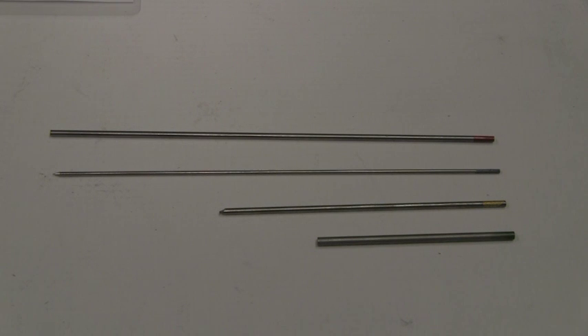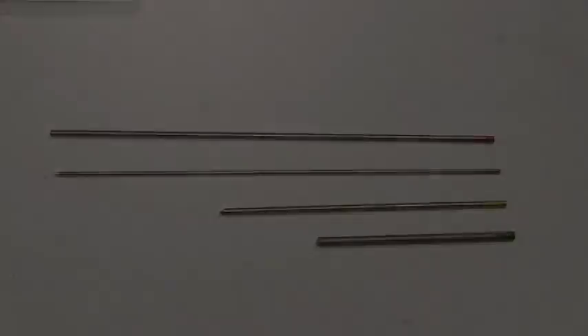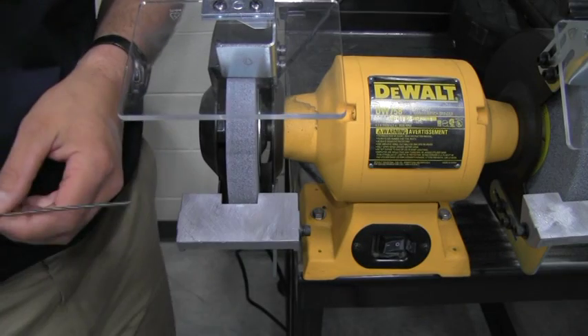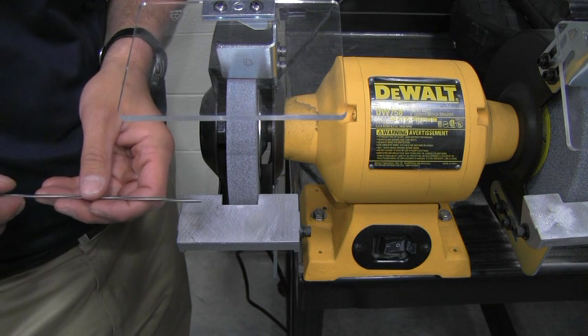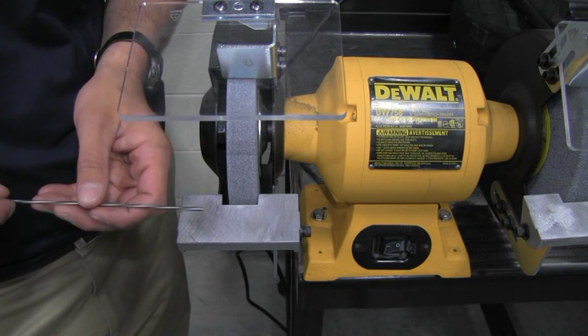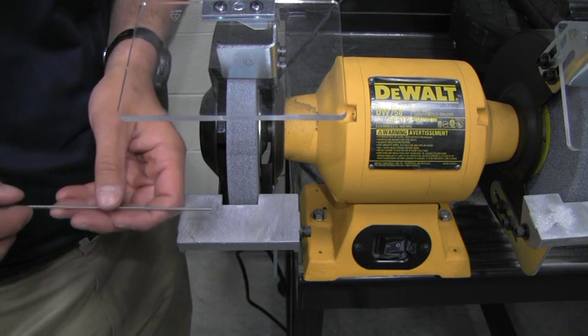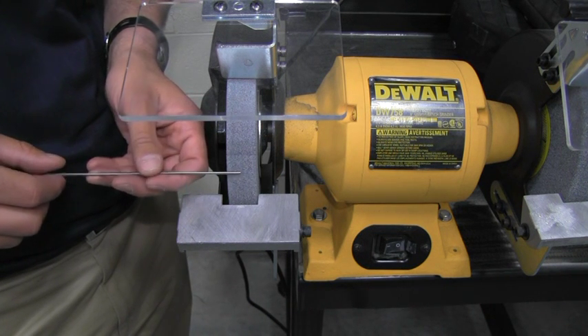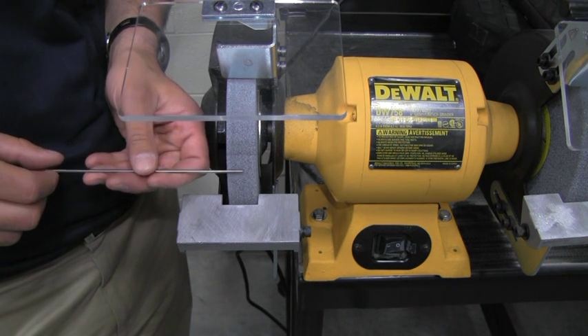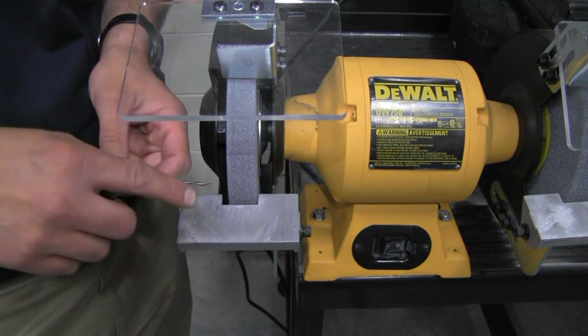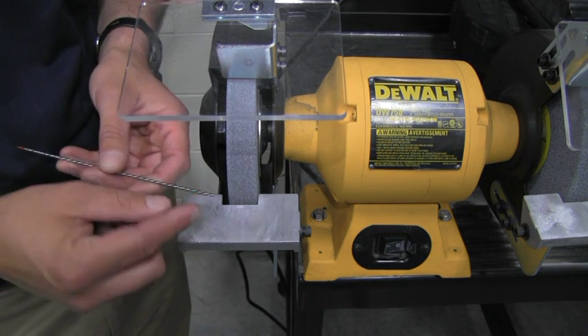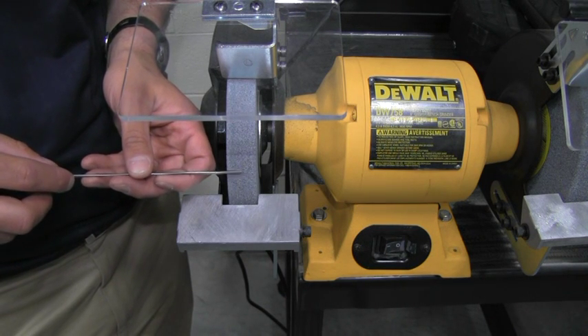Next we're going to talk about the different types of grind angles and how to grind the tungsten properly. So when discussing tungsten, it's also important to discuss the different grind angles and the proper way to grind the tungsten to the point. So this right here, a lot of guys will do it this way. They'll turn the grinder on and, because this is easier, this will put a nice point on it, but this is incorrect. This makes the grind marks in a cylindrical fashion around the tungsten and will cause an unstable arc.